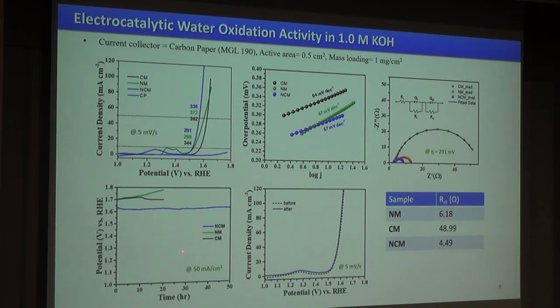And further, the stability of these materials was studied through chronopotentiometry at 50 milliampere per cm square current density, where we observed that NM shows very inferior stability, whereas CM shows comparatively better stability than NM, whereas NCM shows much more promising or excellent stability than these two materials, due to the synergistic interaction of nickel and cobalt in this material, and it shows negligible or almost no change in OER activity after 50 hours. So this NCM material can be considered as a promising electrocatalyst for oxygen evolution reaction in alkaline medium.